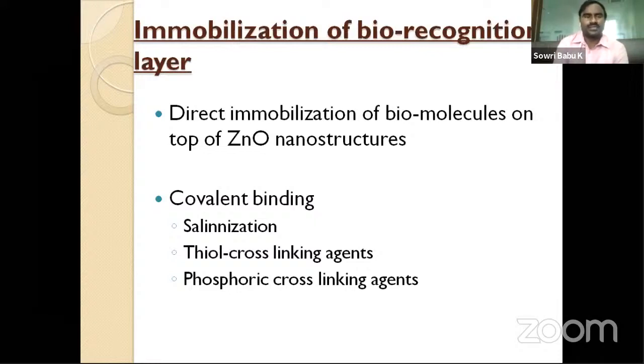So in such a case, what we have to do is add some other chemical to the transducer. That chemical will make a covalent bond, or will act as a mediator to attach the antibody to the transducer. For example, in our case, it is a zinc oxide nanorod. Suppose I want to add antibody to the zinc oxide nanorod, I have to use silanization or cross-linking agents or phosphate cross-linking agents to add antibodies to the zinc oxide nanorods. So this is indirect immobilization.